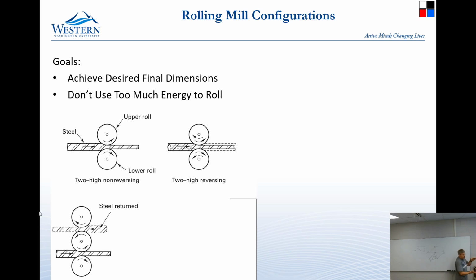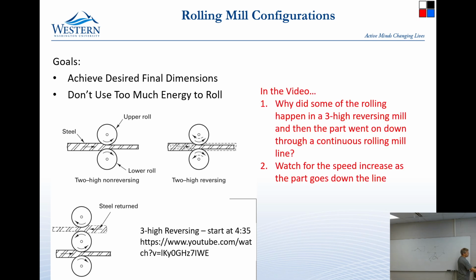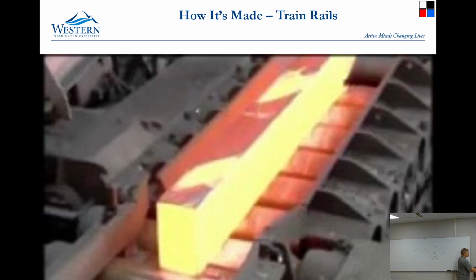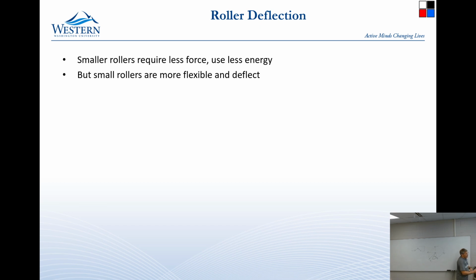Also, as the material gets thinner and thinner, you have to reduce the diameter of the rolls that are rolling it. And so you need different rolls at the beginning than you need at the end. Turns out that making the roll strong enough is really challenging. We're going to go past that for a minute. Because you get deflection of those rollers. If we have a big roller across there, you can see how it could deform the part. But if you get to a small roller, the roller's going to deflect rather than the part.